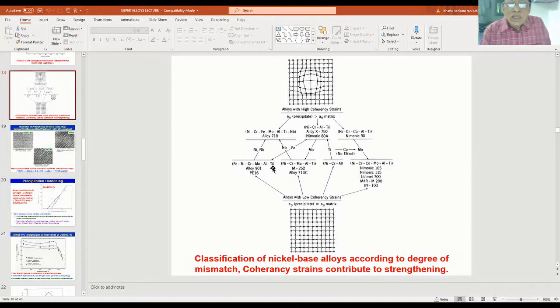For this composition, you add nickel. That means you are increasing the nickel to more than 50%, so then it becomes the nickel base. For that, you add another alloying element, which is known as niobium. Then another phase known as gamma double prime will be coming. Aluminum and titanium will form a gamma prime phase, and niobium, when you add it, forms the Ni3Nb phase. Now, when you add these elements, this gamma double prime phase which is forming there has a higher lattice parameter than that of the matrix. Then you can see how much straining of the matrix is done in the picture that is shown here. So the coherency strains due to precipitation contribute to the strengthening. If the coherency is lost, then strengthening will go down.